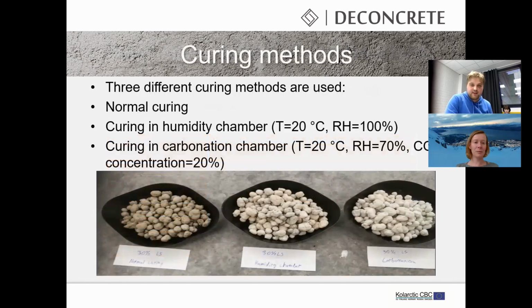And here, I used 3 different curing methods: normal curing in laboratory conditions, then a humidity chamber where the relative humidity is quite high, and then a carbonation chamber with an accelerated carbon dioxide concentration. In the figure are those granules after curing, and it can be noticed that clearly some reactions happen during the curing because the color changes.